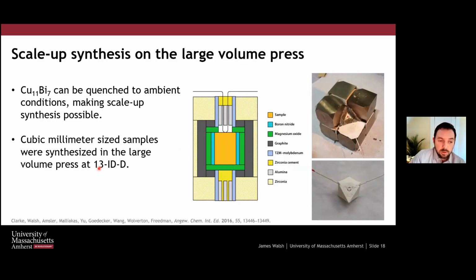And so we did this work at Sector 13 at GSECARS, 13-ID-D. We were able to scale up the synthesis of copper bismuth. And I'm showing here the schematic. This is where the mixture of copper bismuth would go. You have this thermally insulating surrounding jacket. This is a heater, so we can drive a current through the graphite heater, and at the same time we can monitor the temperature with a thermocouple. So we're still able to do our synthesis. You know, as chemists, we want to control temperature and pressure, and we can do that with this setup.